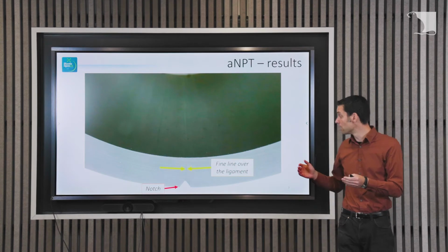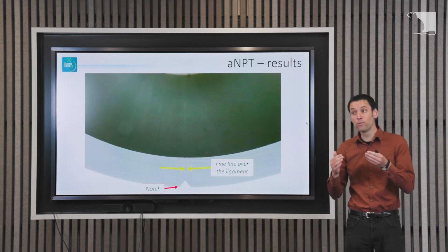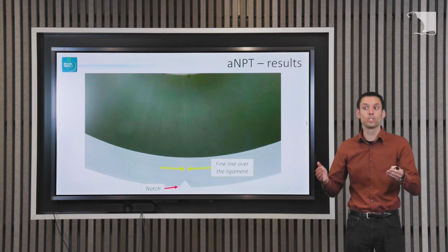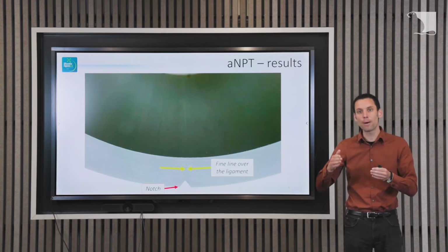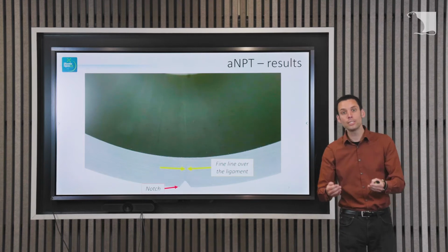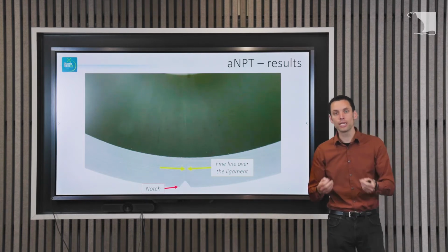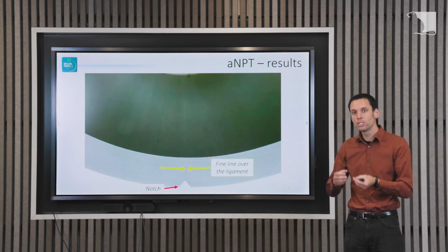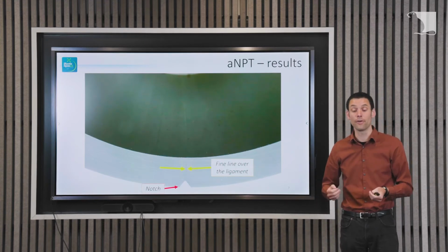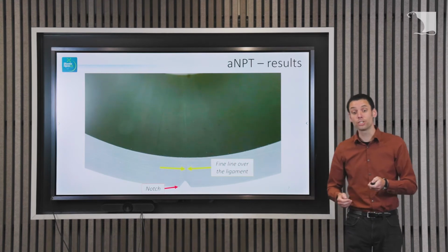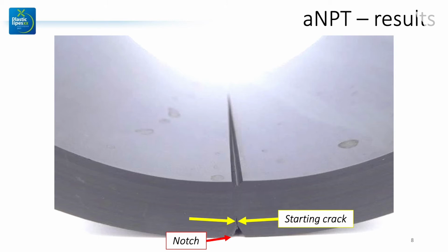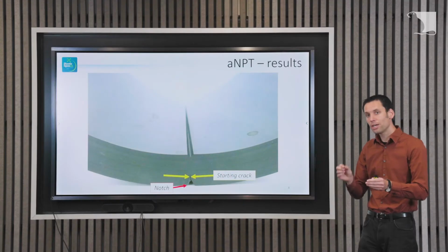I was quite surprised by it because you would expect that a crack would start at the notch tip and you would see something there. But now suddenly we see over the entire pipe wall, before it even failed, we already see a fine line. So apparently something is already happening on a microscopic scale simply due to increased stress in this area. Now if you go to the other notch that didn't fail, but we did see on the inside, we see this cross-section. Again, we see the pipe wall, on the bottom side we see a notch, and in this case we do see a starting crack. But the crack isn't completely through the pipe wall. It's just a starting crack.